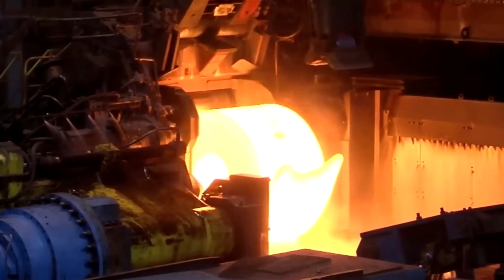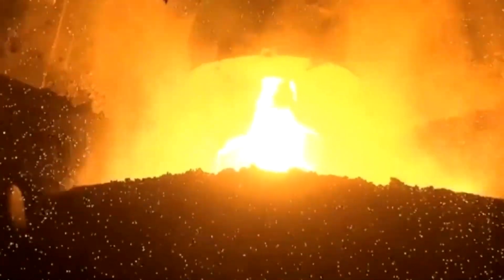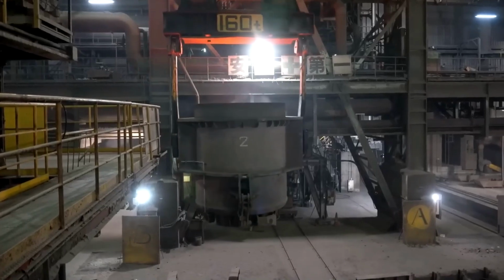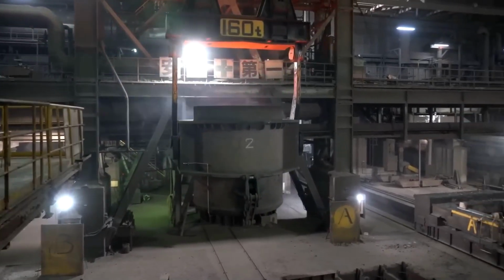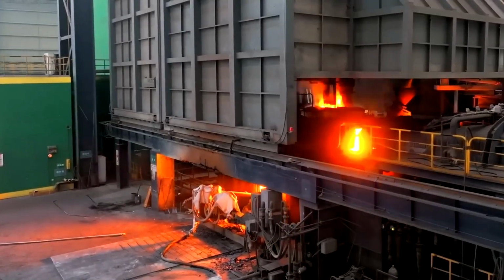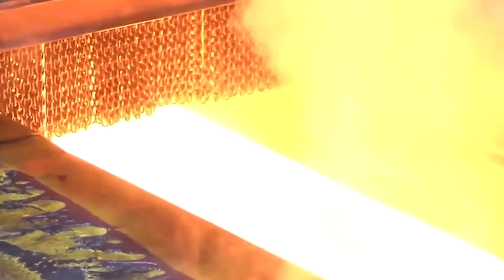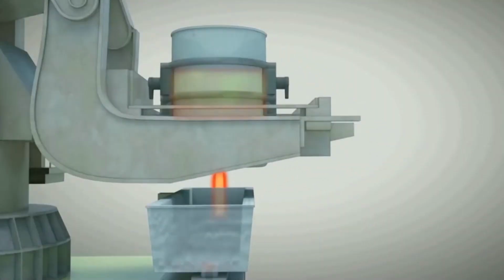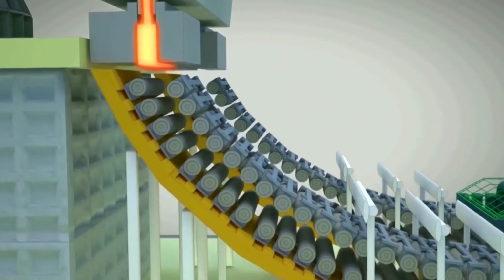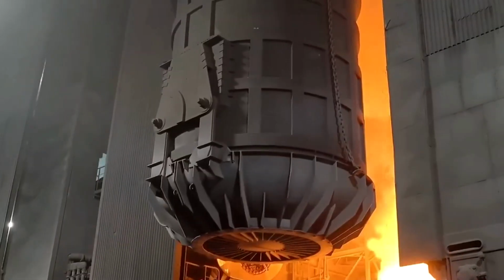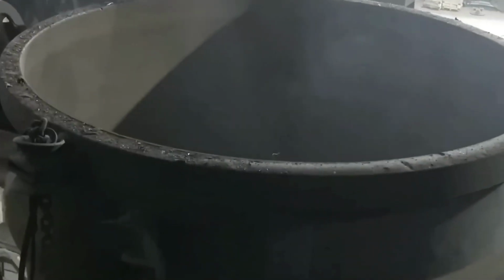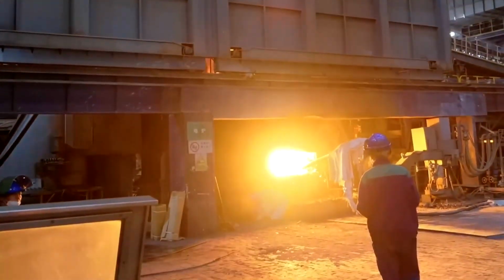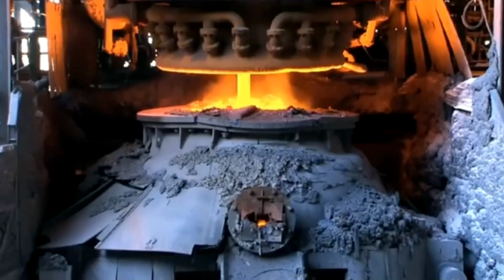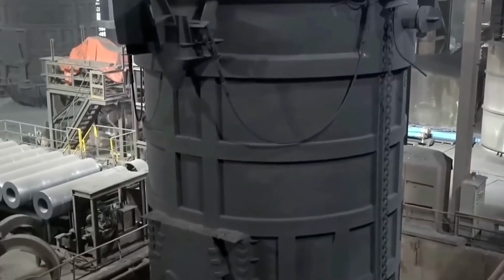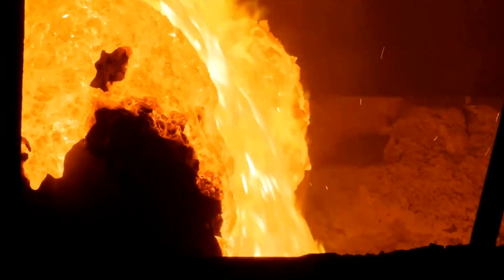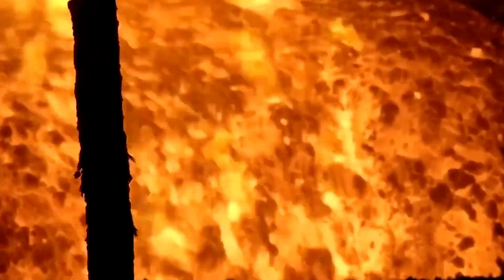This is not the limit of the refinement. Engineers fine-tune the chemical composition by introducing precise amounts of carbon and alloying elements such as manganese, nickel, or chromium to achieve specific mechanical properties. The equipment gradually adjusts the mixture, while sensor systems monitor the temperature and chemical balance in real time. At first glance, this resembles a simple mixing process, but in reality, it achieves a level of consistency and uniformity that often surpasses steel produced directly from raw iron ore. The refined recycled steel reaches its peak quality through this constant digital oversight.